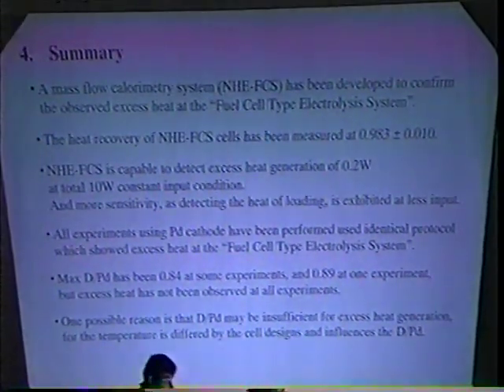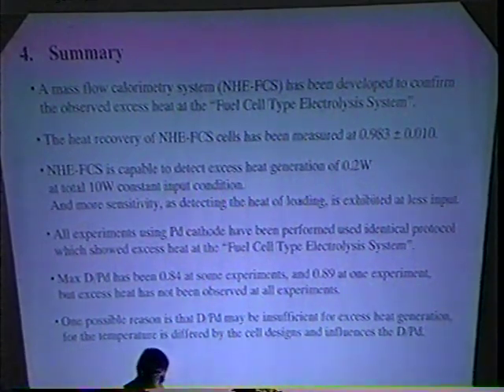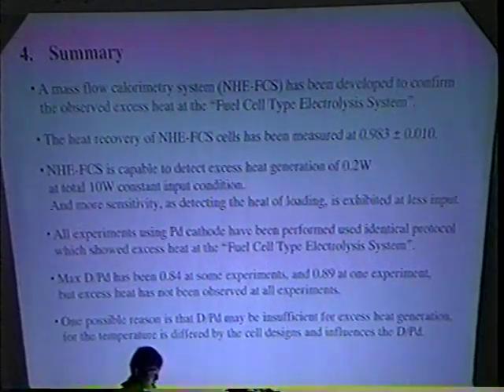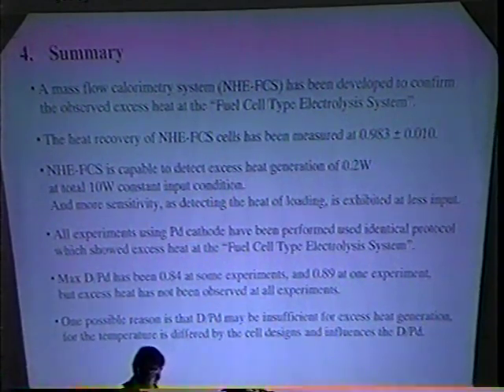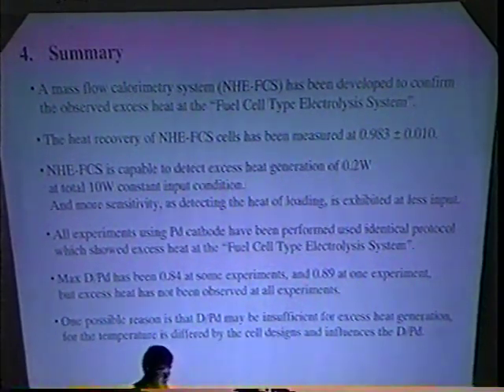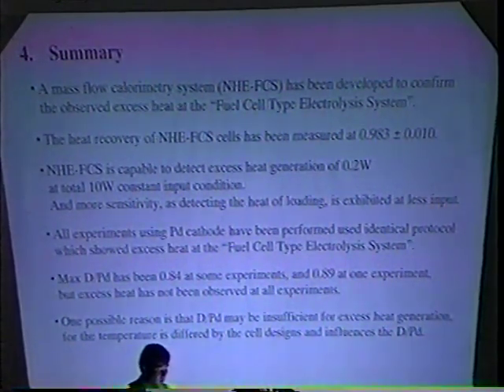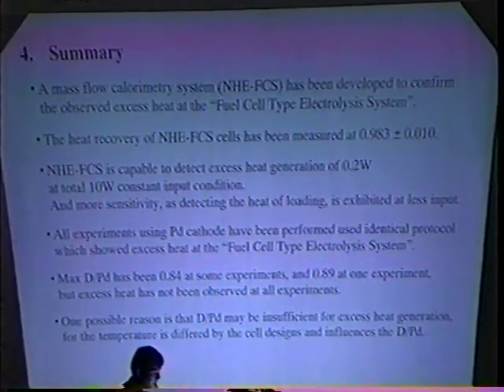A mass flow calorimeter system has been developed to confirm the observed excess heat in the fuel cell type electrolysis system. The heat recovery of NHE-FCS cells has been measured at 0.983 plus minus 0.010. NHE-FCS is capable of detecting excess heat generation of 0.2 watt at a total 10 watt constant condition, and more sensitivity in detecting the heat of loading is exhibited at less input.